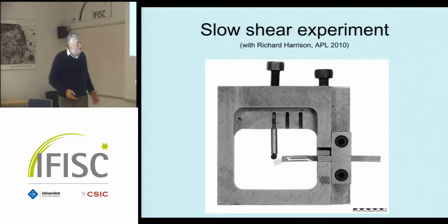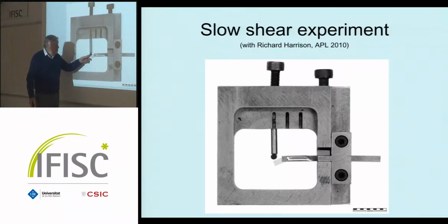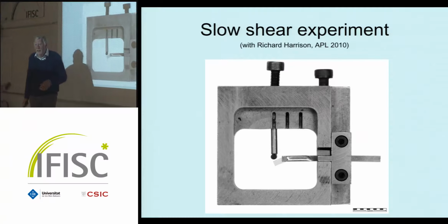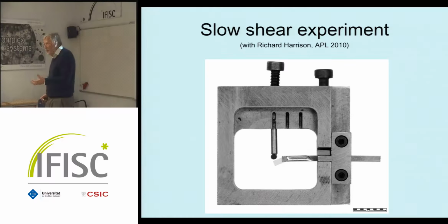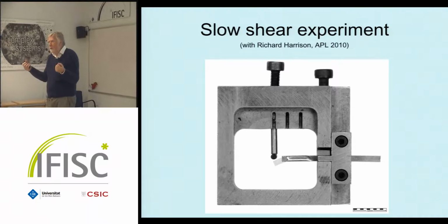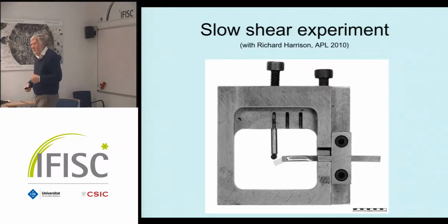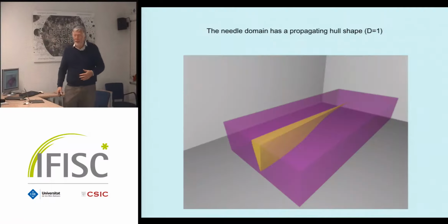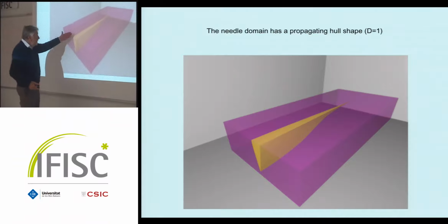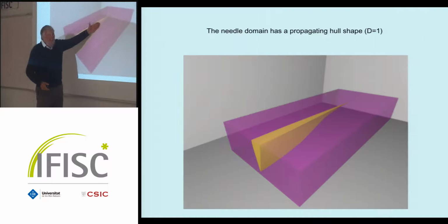So now it's actually not that stupid. This is intelligent because this bit is intelligent. That's for soft matter physicists. They know what it is. It's a soft plastic which you compress, which releases the pressure over 24 hours, very slowly. So when you push it down a little bit, you touch it. So you compress this bead, the round thing, and then it expands over time and increases the pressure linearly. All right, so it's not a stupid device. It's just small. So then you look at it, and so you create a domain boundary, and this domain boundary is now going forwards and backwards. I will show you later a video.